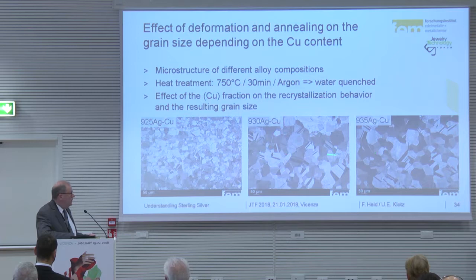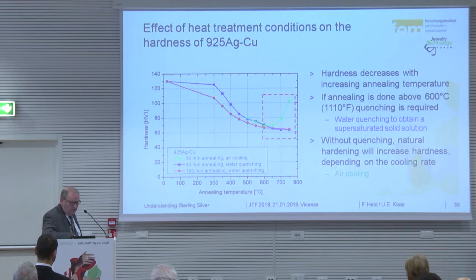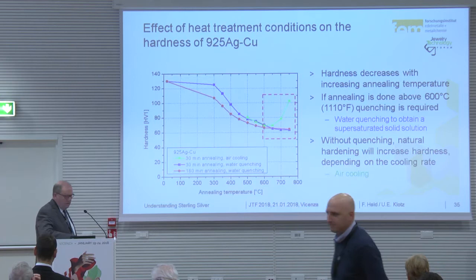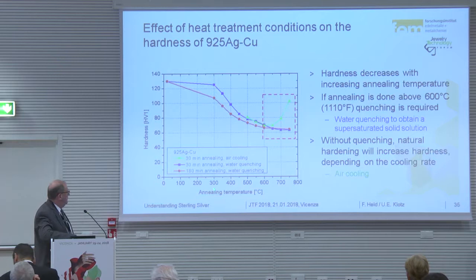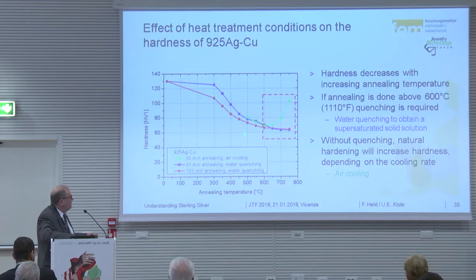Effect of heat treatment conditions on the hardness of 925 silver copper alloy. Hardness decreases with increasing annealing temperature. Here you have 300 degrees, and you see if you want to remove the hardness from cold rolling, it goes down with the temperature, and if we have 400, 500 degrees, we are very low. Sure, we get lower if we go to the higher annealing temperature, but if we use annealing and quench in water, we get lower.